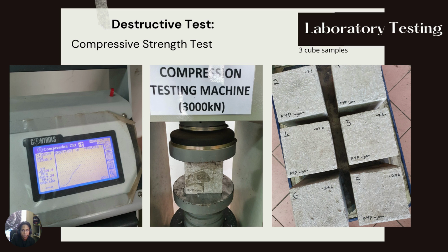Next, for the compressive strength test, which is one of the destructive tests. The aim of this test is to figure out the maximum load capacity the concrete can withstand. The compressive strength test was conducted in a hardened state using a compression testing machine with the pressure of 3000 kilonewton. The average strength was calculated using 3 concrete cubes with the same percentage of dredged sediment substitution of 50% during 7 day and 28 day of curing. After that, the average strength was compared to the conventional concrete cube.